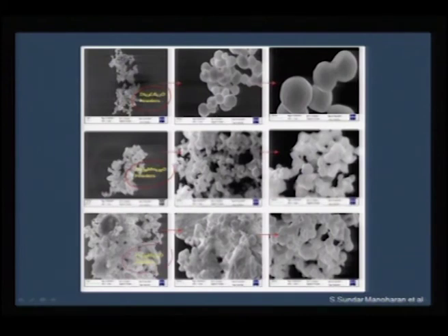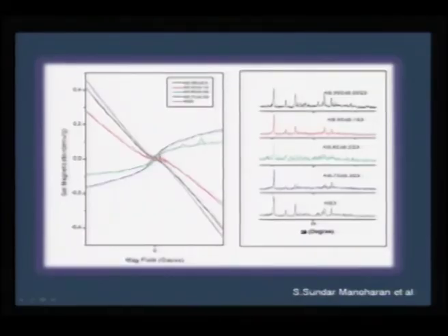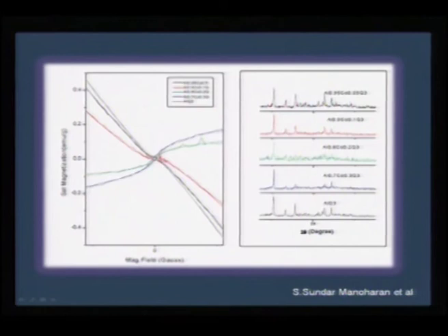As you would see here, even with less than 10% of doping, the crystal morphology or the surface morphology of these oxides change in a variety of ways. In the last two slides I would like to sum up that we can also try to tune the magnetism by using the same solid solution precursor notion by substituting very little amount of cobalt from 0% up to 30%, and as you would see here very clearly, the precursors are showing the same morphology even up to 30% of cobalt doping, but the precursors clearly show a very different trend as far as the magnetic behavior is concerned.